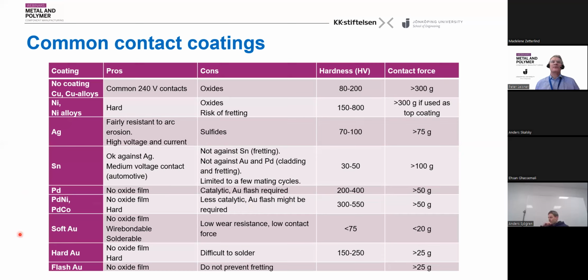Then we have different types of gold. We have soft gold, which is pure gold. It is not wear resistant, but in the microelectronics or circuit boards, you might have on the same component both a contact area and then other areas where they want to wire bond or solder the component to the surface. So it could be a good combination of that. But otherwise for a real switching contact, you would prefer hard gold, that is alloyed gold, which is difficult to solder, but it's harder and you can use it with a low contact force. And the same as for the flash gold used on top. But since it's very thin, it could also be worn away.